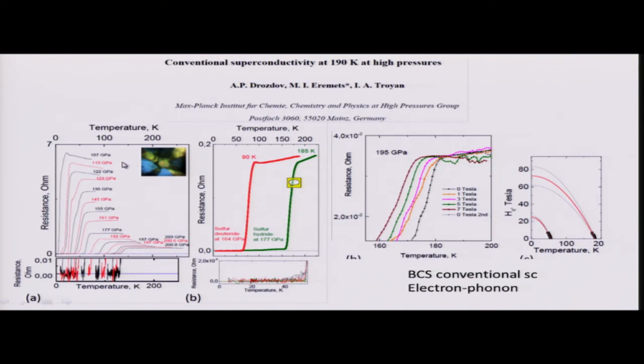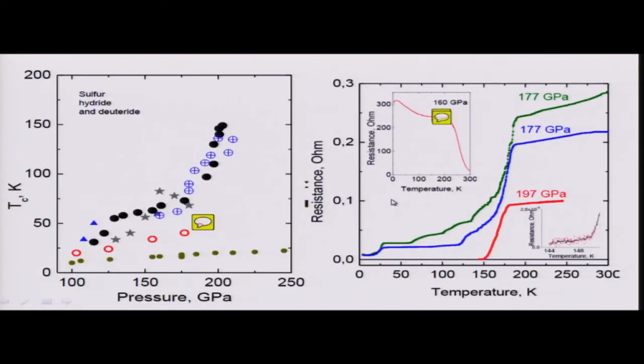The most exciting recent announcement was the so-called conventional superconductivity at 190 degrees at high pressure by Eremets and co-workers from the Max Planck Institute in Mainz. You can see here that under pressure, the material undergoes a phase transition into a metallic state. When you increase the pressure further and further, finally the temperature goes up to 190 degrees Kelvin. And then in order to show that this is superconductivity, in addition to H2S, they also looked at deuterium sulfide. And they saw that for deuterium sulfide, the transition temperature goes down. That's the isotope effect expected if there is electron-phonon interaction. They apply a magnetic field, and they can see the transition actually suppressed down.